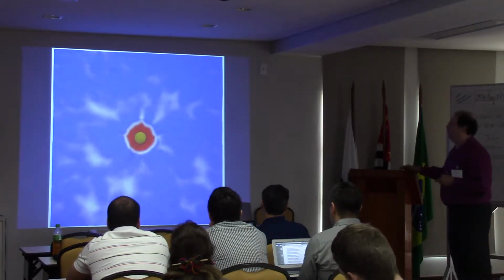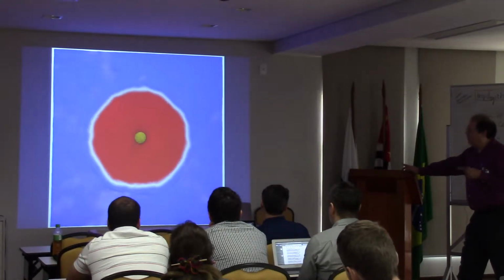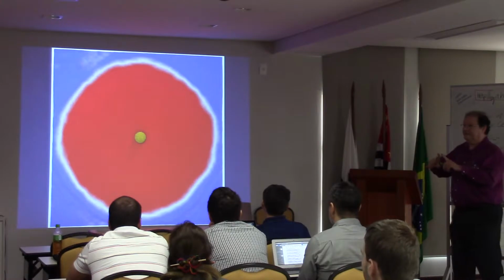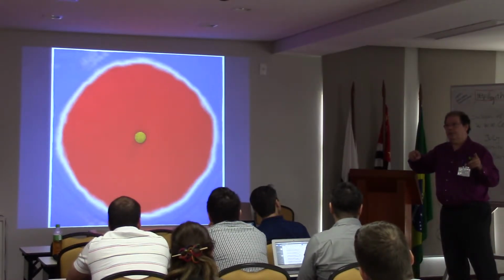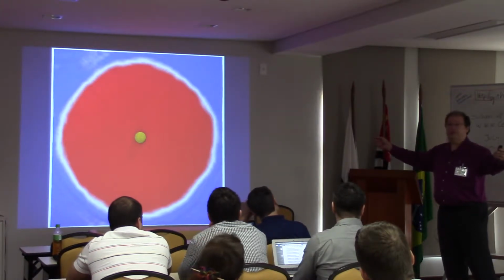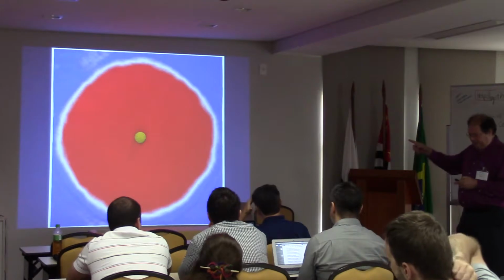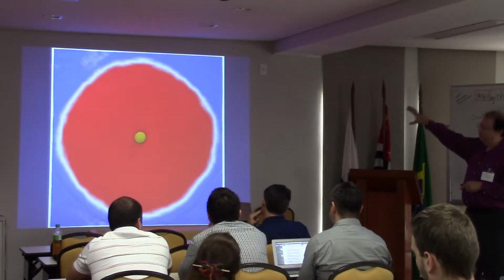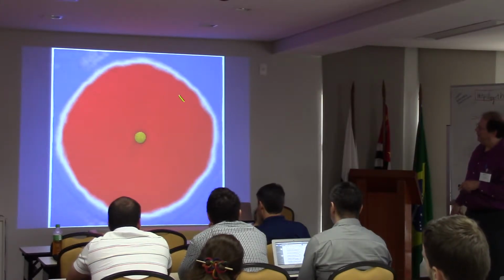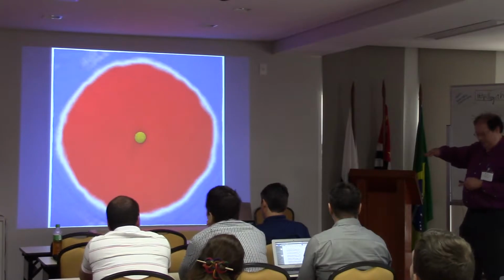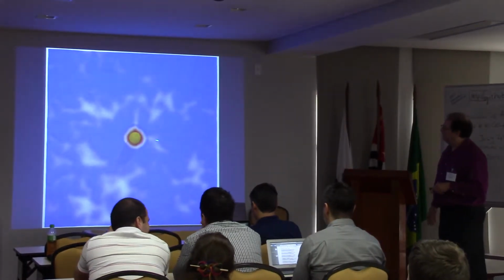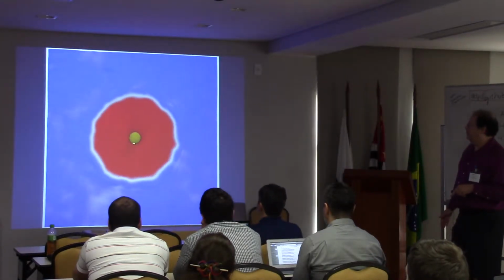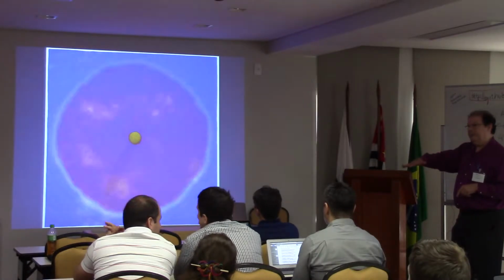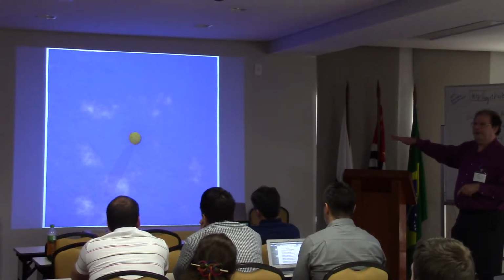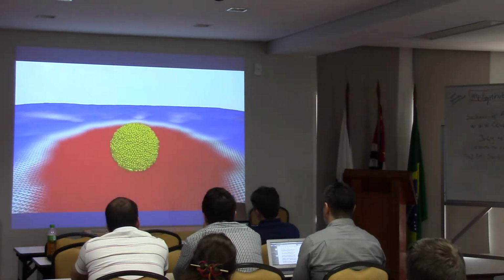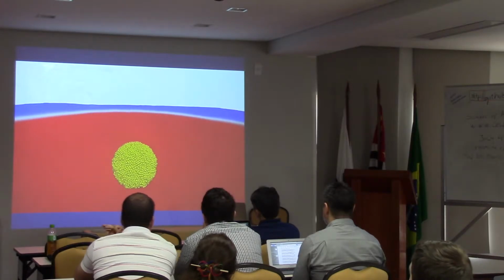We start doing the virtual experiment. We are shooting. One of the surprises of the experimental result is that the shooting creates a very long deformation, much more than they expected. So we ran the first simulation to see if we could capture this effect. You see, beautiful, the simulation. See, the red is below the plane. Let's run again. I'm shooting. This is the blue, it's the zero, and red is below zero. So we are deforming below the plane. You see, it propagates very, very far away. From a different point of view, see, it propagates very far. It's like a meteor impacting the Earth.